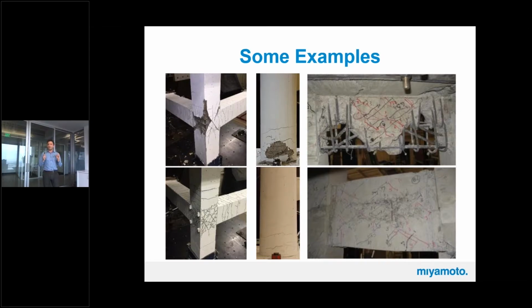For flexural dominated structural elements, fiber reinforced concrete mainly improves the damage tolerance of the element. So you would have a higher number of cracks with limited width. But for shear dominant elements, it changes the failure mode of the element, because fiber reinforced concrete is more ductile and prevents brittle shear failure. Additionally, it increases the shear strength of the system.